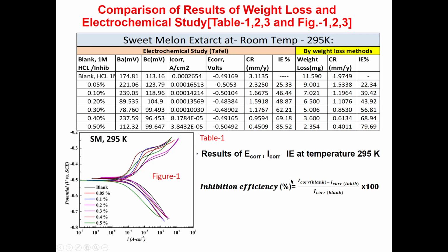This is the data from the electrochemical study and the comparison with the weight loss method. In this method, we find out the E corr and I corr at different temperatures. You can see these values obtained from this analysis, and the graph between the potential versus the current density. When the inhibition efficiency is calculated, you can see that the difference between the weight loss method and the electrochemical study is small, and these are quite comparable. So it is supporting the result that the inhibition efficiency is increasing with the increase in the inhibitor concentration.